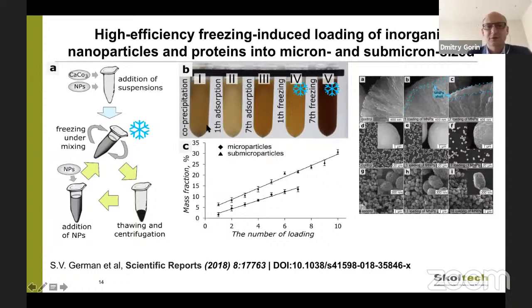Here, this color of suspension is using co-precipitation, adsorption from water solution, and here it's freezing induced. And you see clearly the difference between 7 adsorption cycles and 7 freezing-thawing cycles. It's darker than these tubes. And one of the big advantages of this technology is that you can repeat it if you have a fridge in your kitchen, a fridge with a freezing chamber, and it's enough for loading these particles.